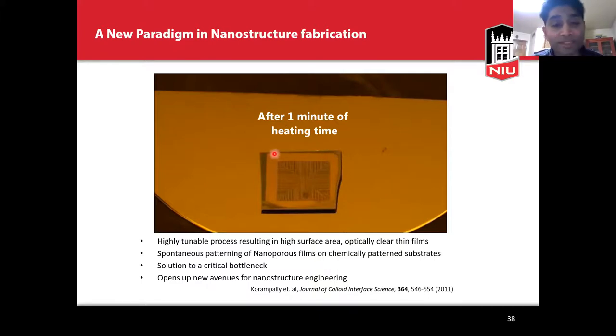We can actually use self-assembly thermodynamics to drive these nanoparticles to assemble in different ways. And our ongoing research is to see if, right now it's binary, we can actually have one or the other. Now we want to see if we can actually get gradient profiles so that we can make the optical structures much more simplistically, as we have demonstrated here. All we have to do is just prepare that substrate, put it on the hot plate, and you get those optical structures within a few minutes. And that basically opens up new avenues for nanostructure engineering.